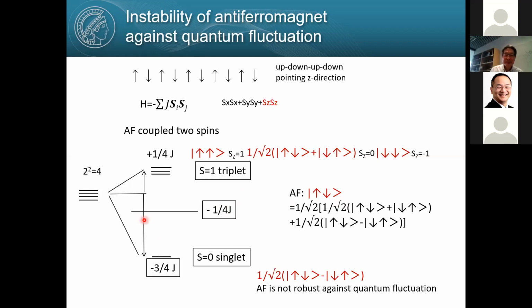So as you see, the spin singlet state has lower energy than the up-down anti-ferro configuration. People often call this anti-ferro up-down state unstable against quantum fluctuation. Quantum fluctuation means a superposition of different quantum states. So that's very basic: anti-ferro is not so stable against quantum fluctuation. In fact, in the early days of magnetism, people discussed that anti-ferromagnets may not exist.